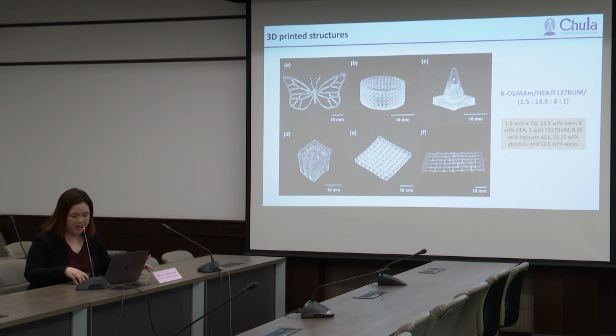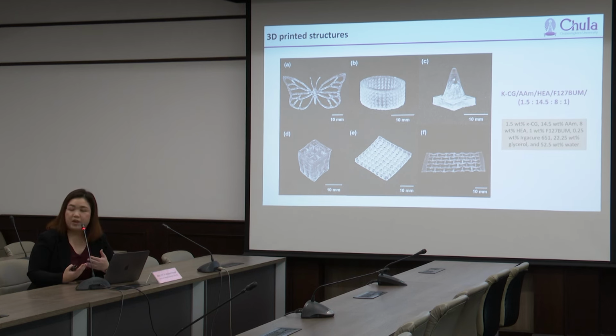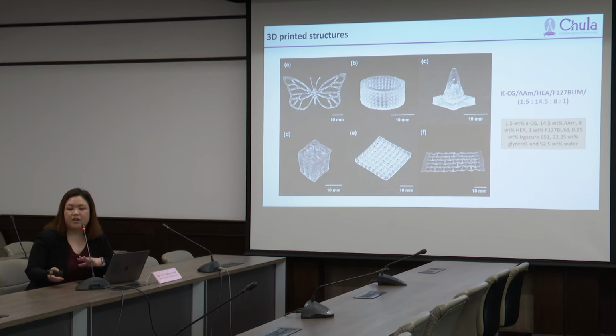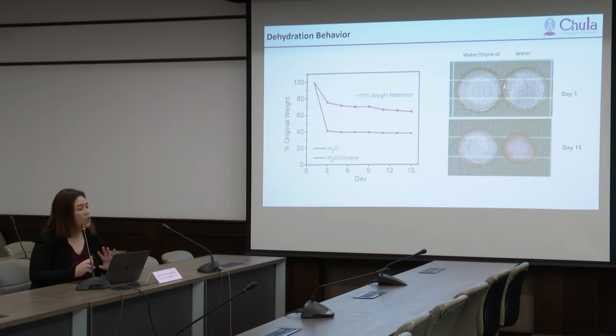And one thing that hydrogels always have a problem with is the dehydration behavior, because hydrogel has a lot of water, right? When you leave it on the bench, the water evaporates. So what happens is that the hydrogel will shrink and the mechanical property will change as well. And it will affect the sensing performance. So what we do in our project is that we add glycerol into our hydrogel. What happened here is that glycerol can prevent the dehydration behavior of the hydrogel.